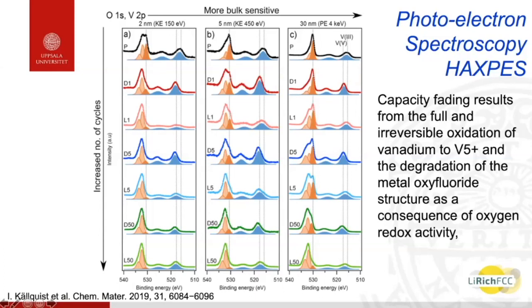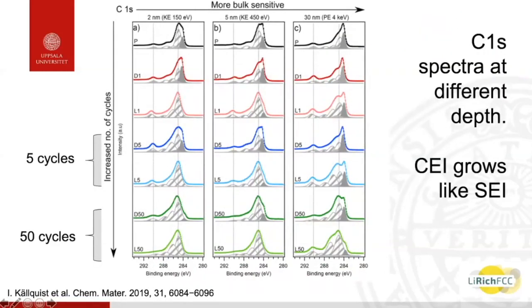And the short story of this is that at the outer surface, the vanadium very quickly becomes redox inactive. So you get vanadium 5+, and you can't do so much. But going in, it takes much longer. In the bulk, it takes about 50 cycles to really reach this inactive situation.